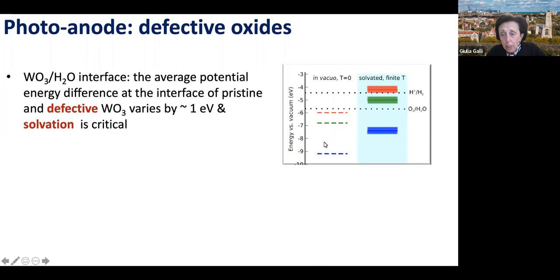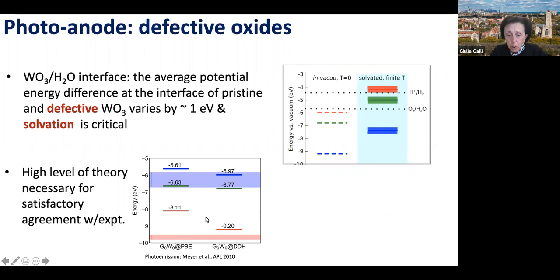So this is a plot of the energy levels of tungsten oxide aligned with the redox levels of water, valence band and conduction band, derived from the electron affinity that I told you about. On the left-hand side, dotted lines, you have the results that you would get if you do calculations in vacuum and at T equals zero. Then on the right, I plot what we got by doing calculations at finite temperature for solvated samples and by doing defective solids, and the green line here is the level that you have because you have oxygen vacancies in the system.